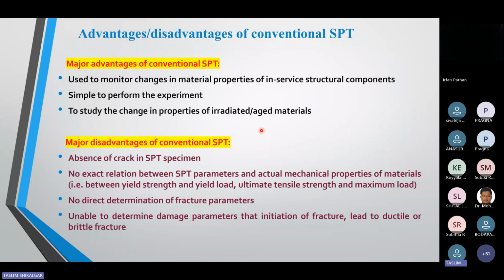Advantages and disadvantages: we can use this type of specimen to monitor changes in the material properties of in-service components. These specimens make experiments easy to perform compared to standard experiments. And this testing methodology can be used to study changes in the properties of irradiated or aged materials. But one of the major disadvantages of SPT is the absence of a crack in the SPT specimens, so we are unable to get fracture properties. There are no exact relations between SPT parameters and actual mechanical properties, like between yield strength and yield load, and ultimate tensile strength and maximum load. There is no direct determination of fracture properties with conventional SPT specimens, so we are unable to determine damage parameters. These are important to find the initiation of fractures or whether they lead to ductile or brittle fractures.